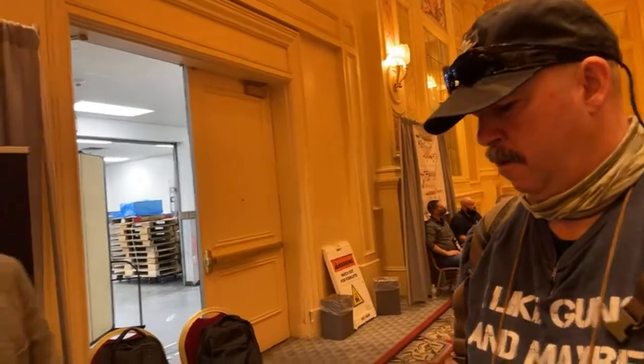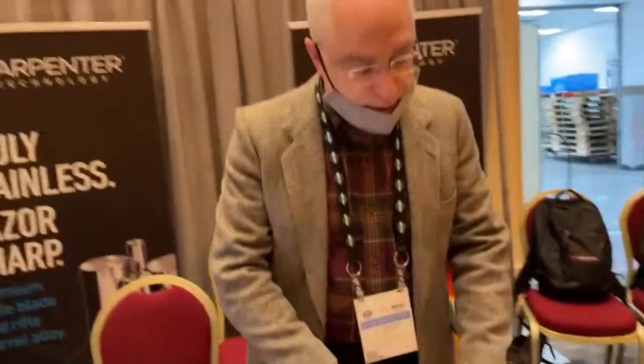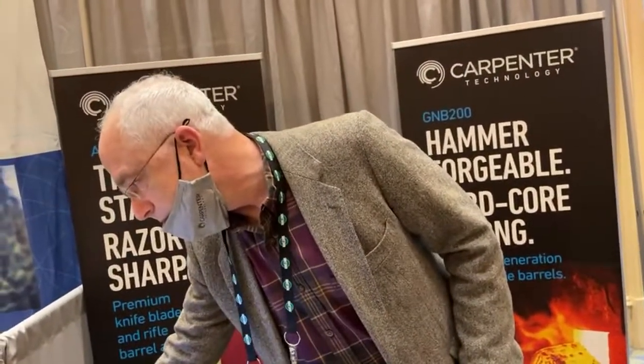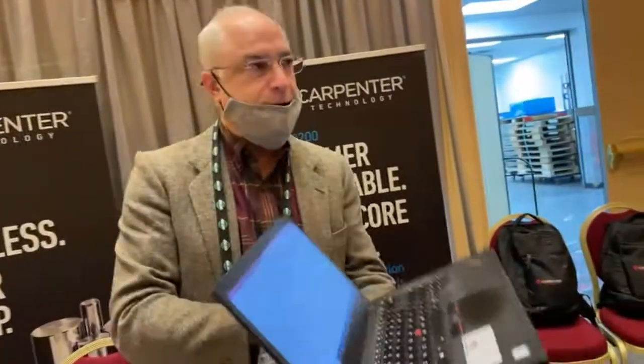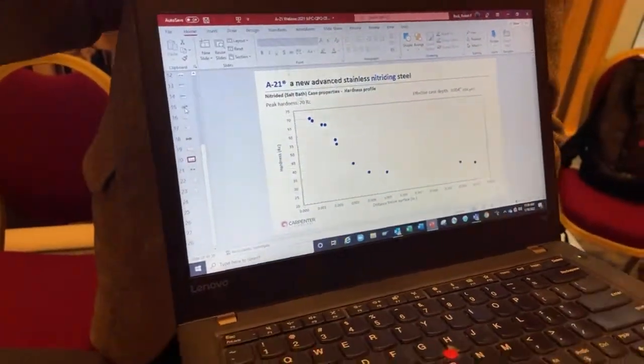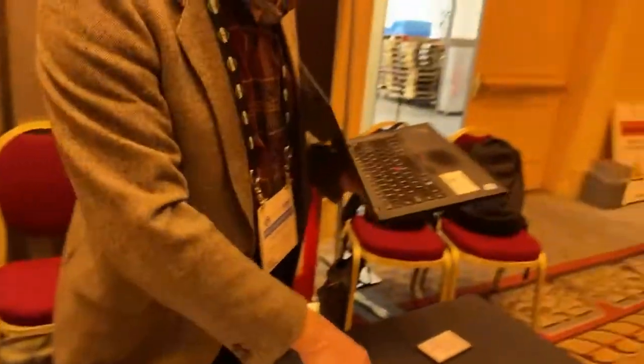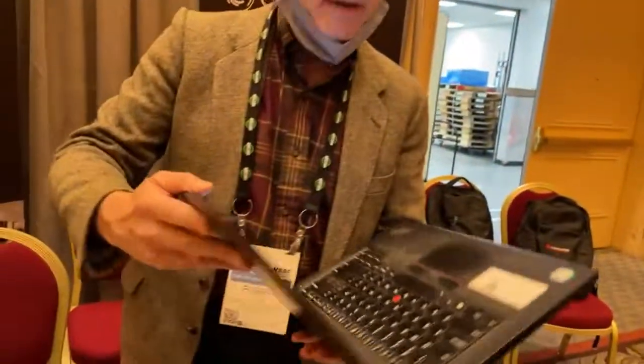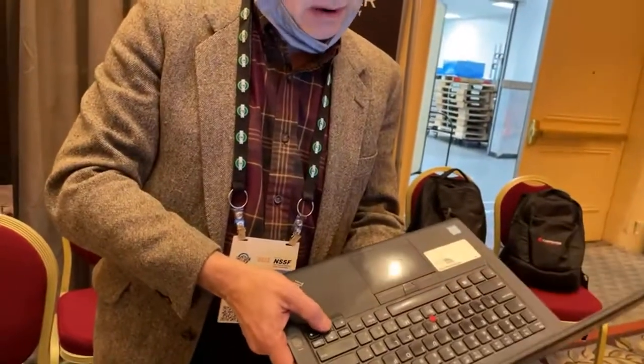And we can actually nitride where we hit 70. And if I do both, if I do carburizing, what I just showed you here, this is nitriding. This is salt bath nitriding, so it comes out black. I can hit 70. Now the difference is it's only 2 thousandths thick, not 80 thousandths. That's the trade-off. But if I do both, I can hit 73.